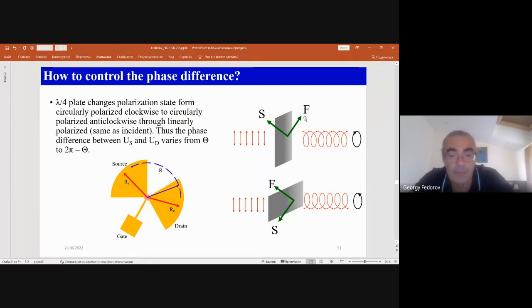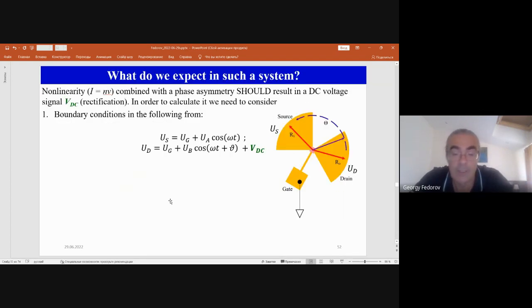And not to go too deep into geometrical issues here, to prove that the phase is tunable by rotating this λ/4 plate, we just consider two cases: circularly polarized radiation that goes this way, and you have a phase difference on one side. You start rotating the other way, and you have a phase difference between two signals here on the opposite side. When I say signals, I mean the potentials of the source and drain electrodes with respect to the top gate electrode, which I consider as the ground, the local ground of the experiment.